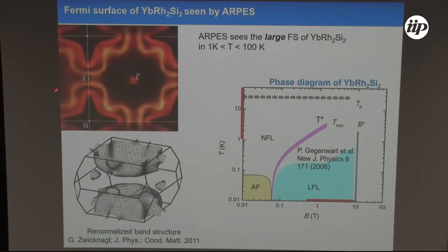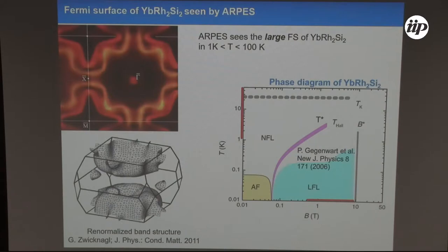We performed temperature measurements of the Fermi surface looking precisely at the neck region and along the diagonal. The large Fermi surface is rather robust in size — it always remains large down to 800 mK and up to 100 K, a temperature much higher than the Kondo temperature. Since the large Fermi surface for this compound persists down to 800 mK, we believe this is an essential point for the interpretation of the phase diagram of ytterbium rhodium disilicide — in particular for the interpretation of the origin of the quantum critical point in relation to the spin density wave scenario.